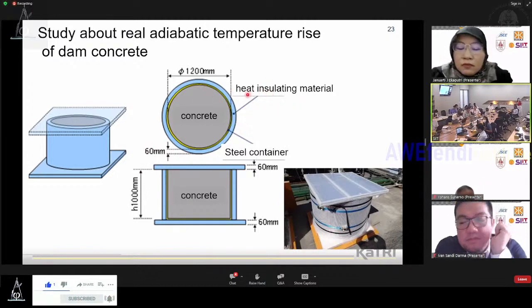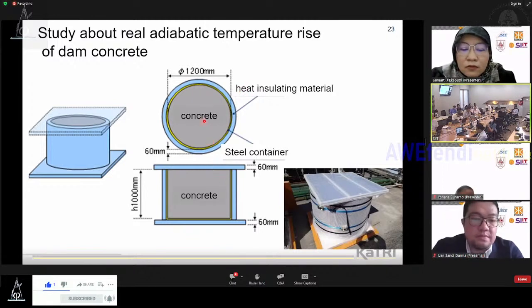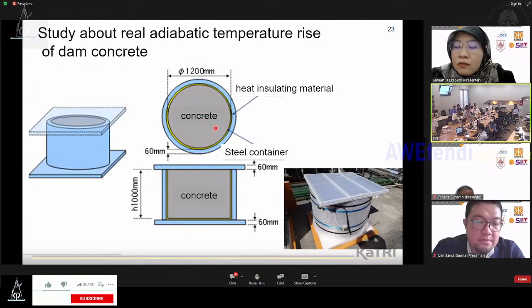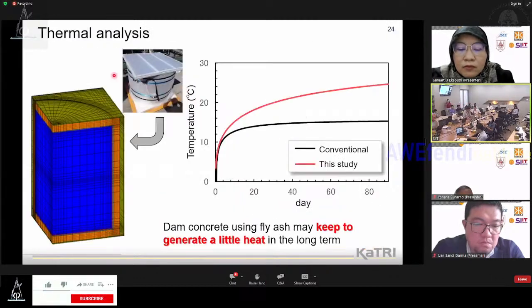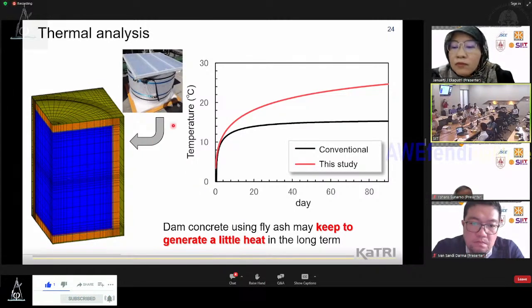equipment. The heat insulating materials, the sealing container, and the concrete. We put the concrete in the seal and measure the temperature inside the concrete, and then we try to simulate this equipment in the thermal analysis. With this, we get the adiabatic temperature rise of fly ash concrete.